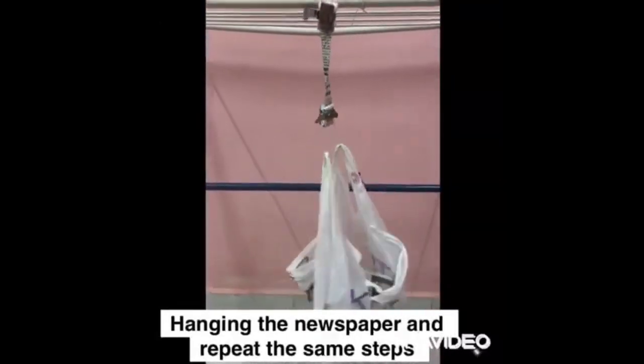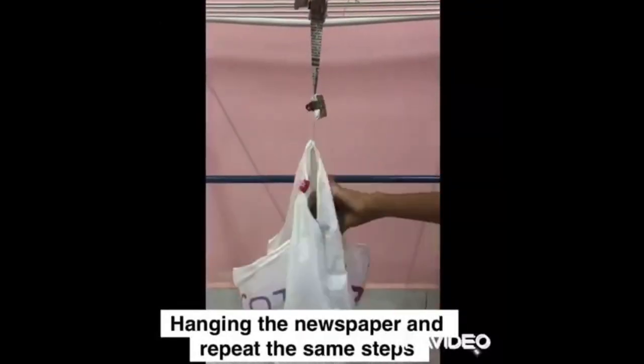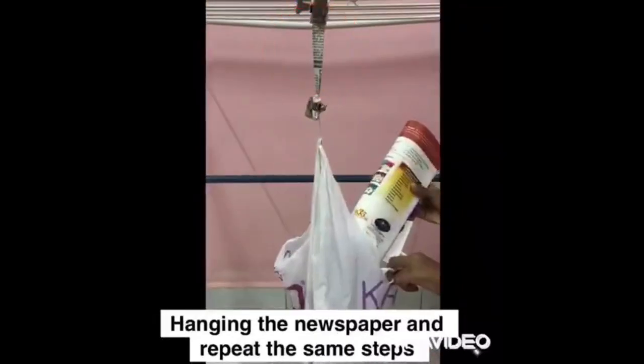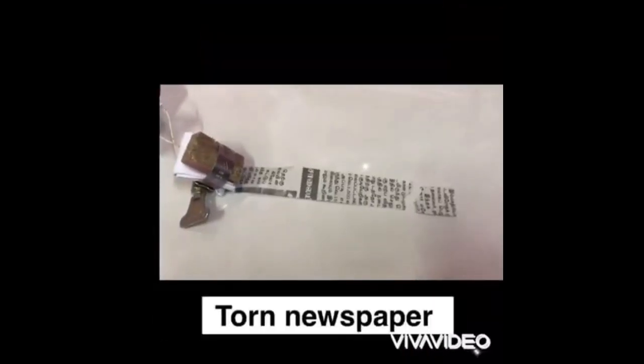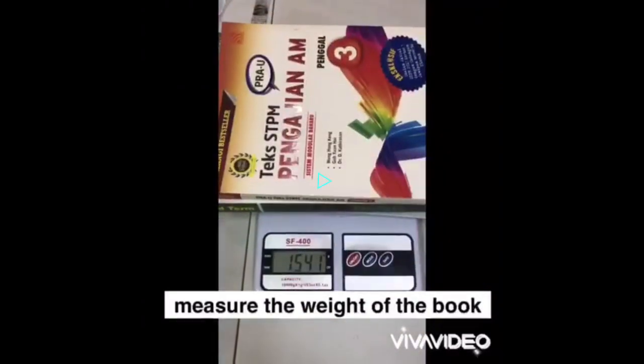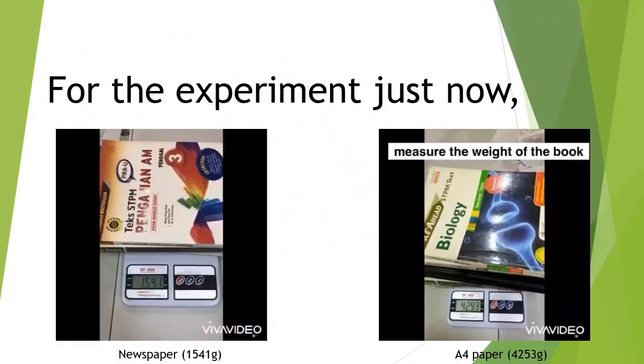After that, hang the newspaper and repeat the same steps. Torn newspaper. It's necessary to measure the weight of the book. For the experiment just now, we compare the strength of newspaper with the A4 paper. The load that can be withstood by the newspaper before break is around 1,500 grams, while for A4 paper is around 4,000 grams. They are tested in the same direction, so why is there so much difference between the strength of newspaper and the A4 paper?